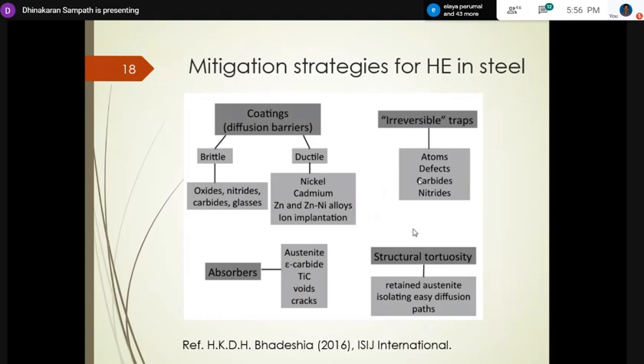The reason is that hydrogen that is freely moving in the matrix is what creates the cracking problem. Sometimes these traps also become a problem, but for one-time exposures to hydrogen, such as welding or electroplating, these will absorb the hydrogen, and then the material will function as usual, as normal. And there are other similar irreversible traps, absorbers. Again, they are all strong traps. They just absorb hydrogen and never release it. Only at very high temperature do they release hydrogen.